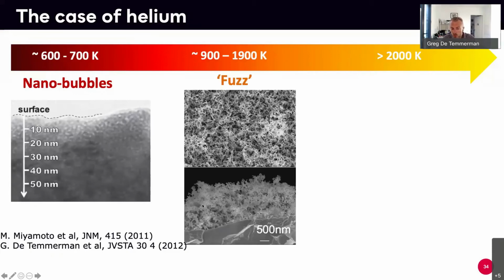If you increase the temperature, your material starts to swell in the form of filaments which grow out of the surface. This is what you will see on the top. You see very tiny filaments, about 20 nanometers in diameter, growing in a random way out of the surface. This is not something deposited on top, but the helium making the surface swell and form those filaments. And the problem is that you can just take a wipe and wipe that away. So it's creating, or it could create, a lot of impurities in the plasma.